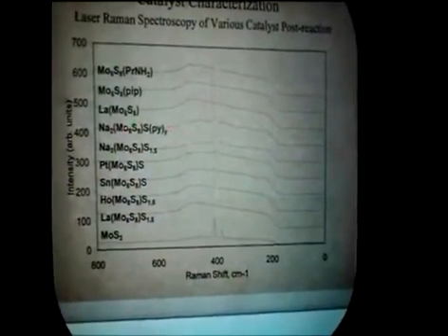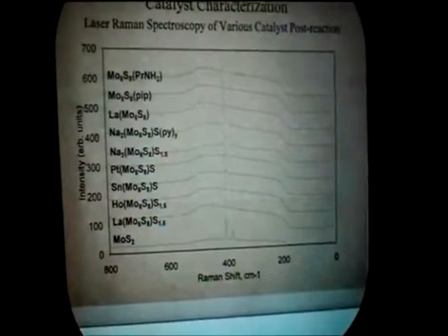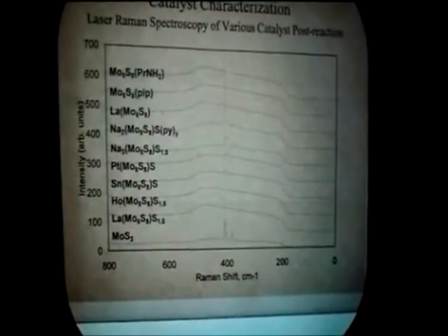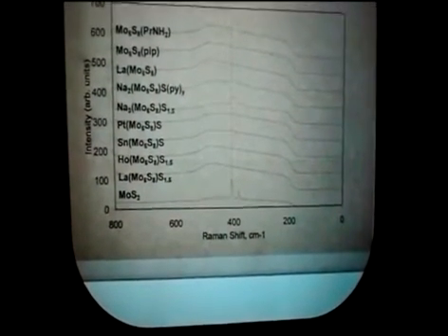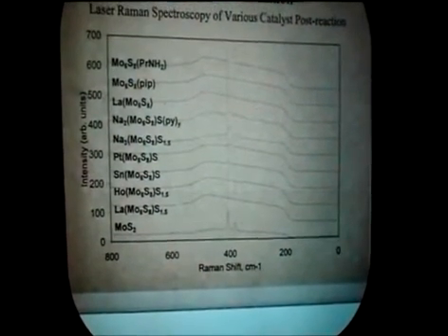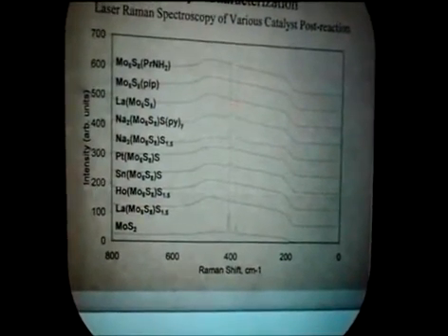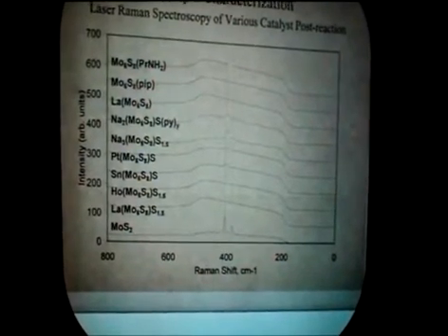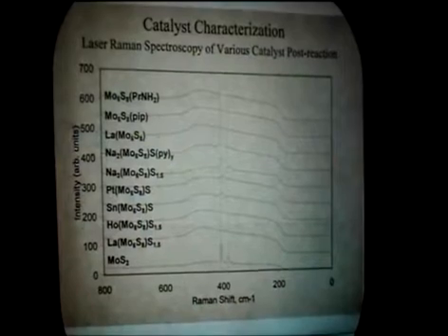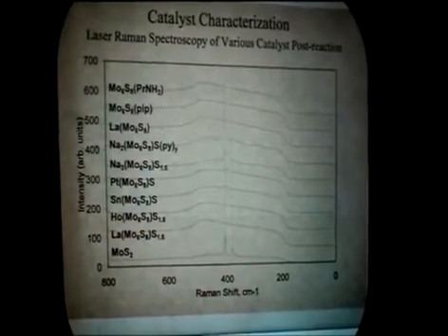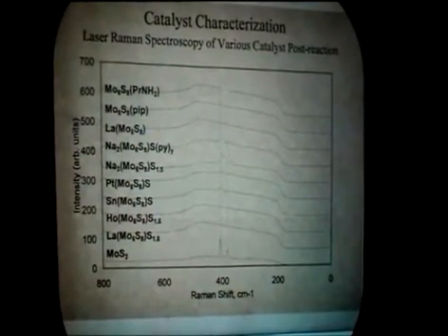What we can see right away is that these sodium materials show formation of MoS2, and this is after 20 hours at 250 degrees C. We also see a little bit in the tin and maybe a little bit in the platinum. The lanthanum Chevrel phase showed no conversion to MoS2, and neither did these ligated molecular complexes, which is a bit surprising, since 250 degrees C is above the minimum temperature required for deligation.